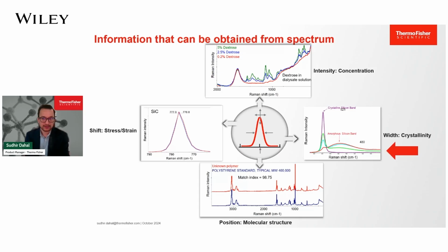Shifting our focus to the right, the set of spectra emphasize the significance of spectral bandwidth, which is crucial for determining crystallinity. Narrow bands are indicative of crystalline structure, while broader bands, as shown here, suggest an amorphous structure. Lastly, the spectra on the left demonstrate subtle shifts in peak position within the same sample, really. These shifts are indicative of stress and strain within the material. By analyzing these various facets of Raman spectra, we can attain a comprehensive understanding of materials' properties and behavior, using simple examples like shown here.